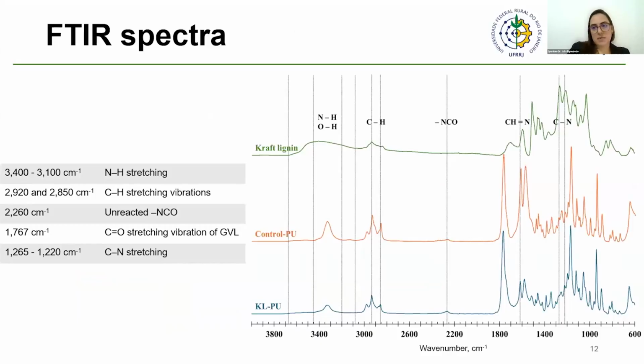So after we synthesized the polyurethane, we ran an FTIR to evaluate if we really formed the polyurethane. When we did the formulation, we made a control sample too. This control sample was without lignin because with DABCO in the medium, GVL can react with isocyanate and form polyurethane. So to rule out the interference of GVL in the formulation, we ran this spectrum too. And we noticed with the FTIR spectra that the characteristic bands of polyurethane in both formulations were present.